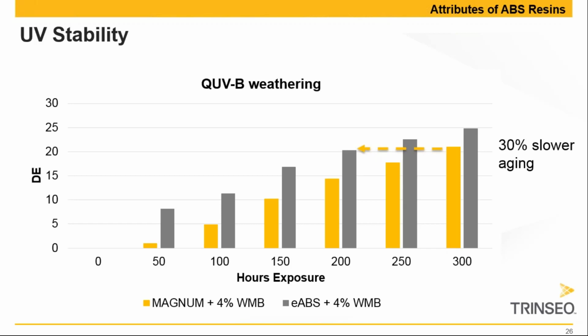Something extra on UV stability. Now we move from QUVA to QUVB weathering, which is a more stringent UV exposure test as it simulates more outdoor accelerated conditions. And there we see that the Magnum ABS ages about 30% slower than emulsion ABS. So again, in theory, you could reduce the amount of UV absorber in comparison to emulsion ABS with about 30% in case of bulk loading into the ABS.